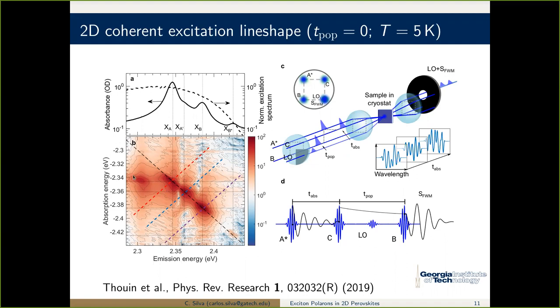And so, at first instance, you see nothing more than what you measure in your linear spectrum. Here's my exciton A, my exciton B. There is some substructure that I can resolve with this two-dimensional coherent excitation spectrum. Here on the diagonal of this absorption and emission axis, my two energy axes are coherently correlated. I see the same features on the diagonal as I would see in the linear spectrum, but I also see cross peaks. Here's a biexciton. I'm not going to tell you why it's a biexciton, but this is a biexciton. In fact, they're bound by something like 50 millielectron volts, also very strongly bound.